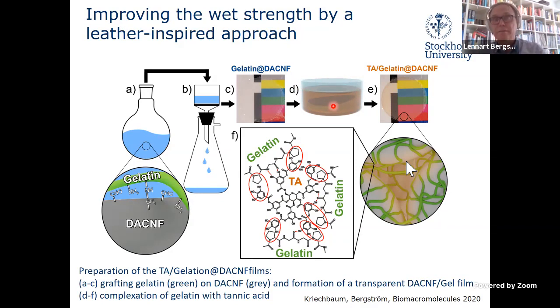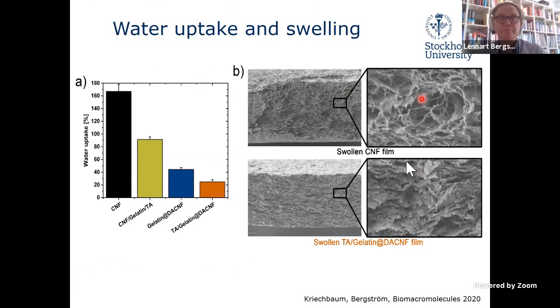The tannic acid then reacts with the gelatin, precipitates the gelatin, and then we get this brownish film with a slight brownish color. And that is then the tannin-gelatin-CNF composite. I'm going to go through the properties of this material in some detail.